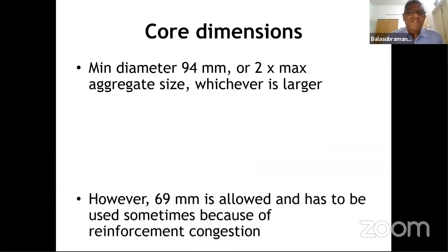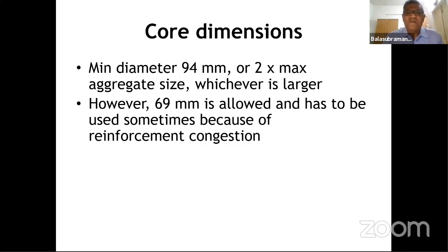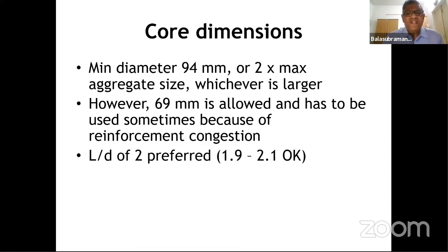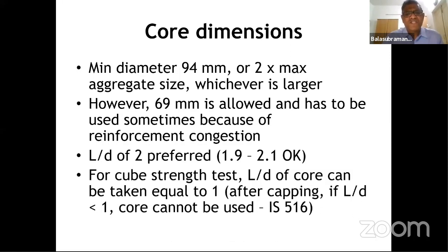So what is the core dimension? Generally, it says minimum diameter 100 mm or 94 mm. But today, the congestion of the reinforcement is so much that we are not able to take a core. Suppose that the core is 100 mm diameter, then the inner diameter is approximately 94 mm. Sometimes the congestion of the reinforcement is so heavy. Most of the time, every year we are taking a few hundred cores, and then generally we are going for a 69 mm diameter core, because cutting of the reinforcement has to be avoided to the extent possible.